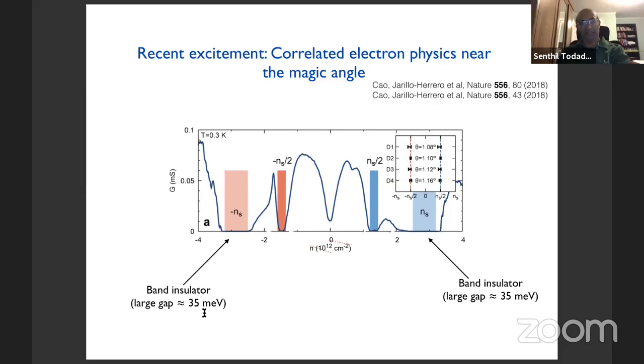The transport measurement, by measuring the temperature dependence of the conductance, you can extract out an estimate of the gap. And the gap turns out to be big. It's about 35 millielectron volts. Okay. So these two endpoints are band insulators. So everywhere in the middle, you have a situation in which these flat bands are partially filled.